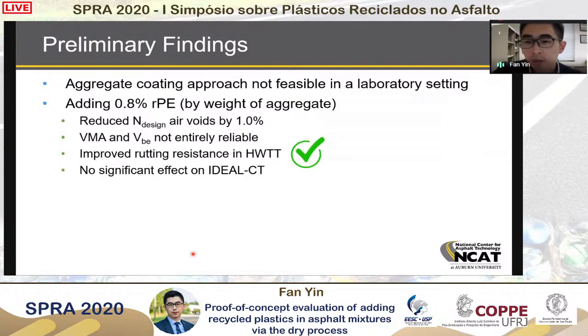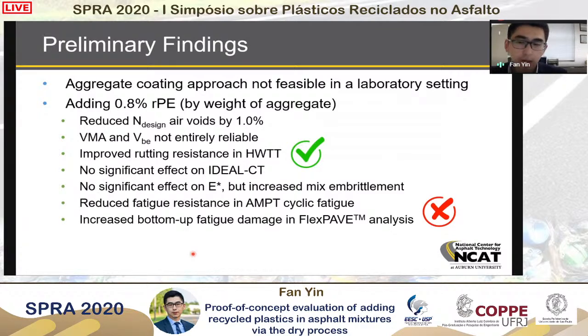In terms of rutting resistance, we saw improvement in the high temperature behavior, which is a positive sign. We did not see any significant impact on IDEAL-CT. But when we look at the AMPT cyclic fatigue and also the FlexPave predictions using the bottom-up fatigue damage model, we realize adding plastic can have a negative impact.